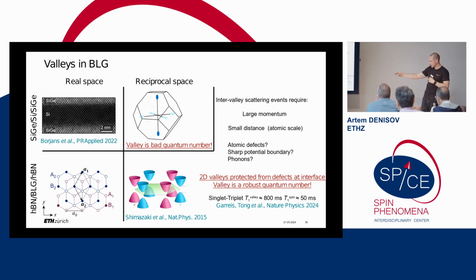Yeah. In fact, just 1 year ago in our lab, it was demonstrated that when you make singlet-triplet qubits, singlet-triplet T1 for valleys is indeed 1 order of magnitude longer than for spins. And T1 for spin is also very good, 50 milliseconds. It's what state-of-the-art silicon qubits have with the artificial spin orbit. So our idea was, if spin is a decent quantum number and valley is a very good quantum number, why don't we combine the two to make a qubit where the only process which will lead to relaxation will be a second order process. So this qubit should be super protected from the environment, and have a very long relaxation time.